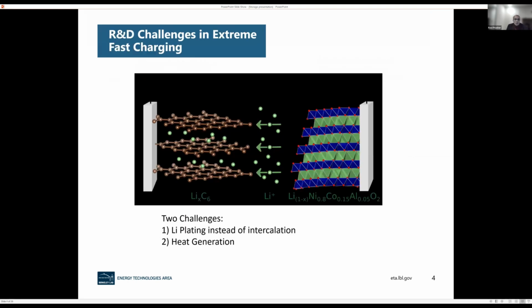So there are two challenges when you do extreme fast charging. The way a lithium-ion battery works is that you have a cathode, which is, let's say, lithium nickel cobalt oxide cathode here. And when you're charging the battery, the lithium moves from the cathode side to the anode side, and the anode is typically made of graphite. And the lithium goes and sits between the graphitic planes, right? So nicely it goes and nicely sits.